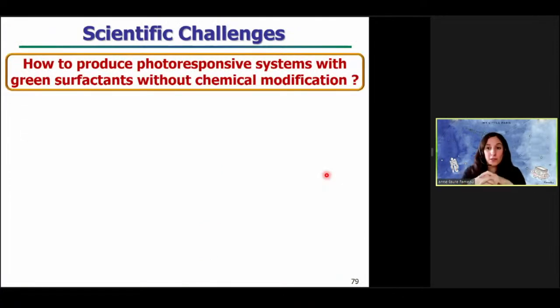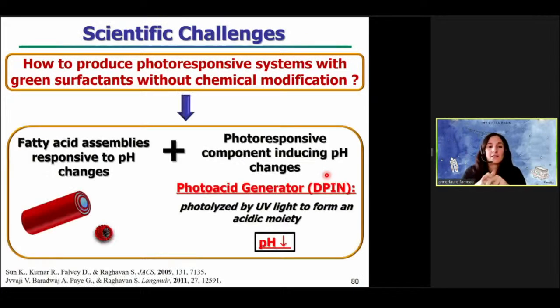Another approach that we used to design this kind of photoresponsive foams was based on the fact that fatty acid assemblies are known to respond to pH changes. And so we just combined these fatty acid assemblies with photoresponsive components, which are known to induce pH changes under UV radiation. As photoresponsive component, we used a photoacid generator, diphenyliodonium nitrate, that is known to get photolyzed by UV light to form an acidic moiety. So you apply UV light and you observe a pH decrease.